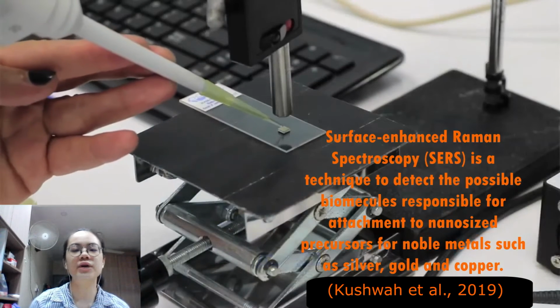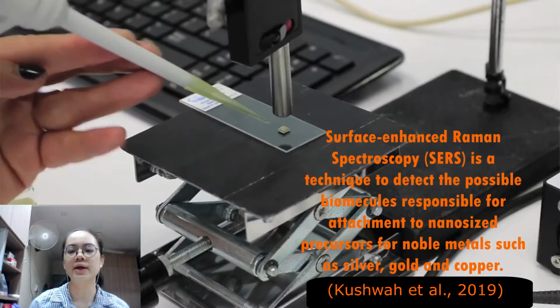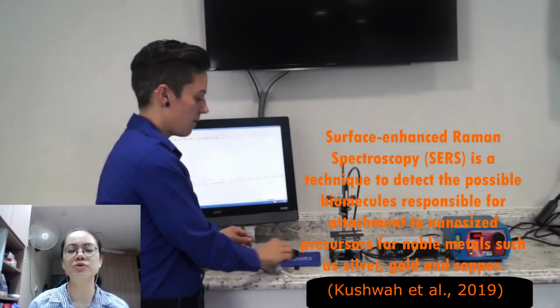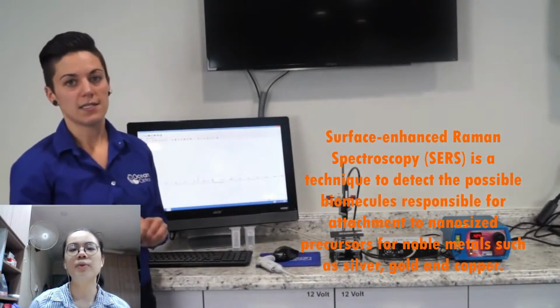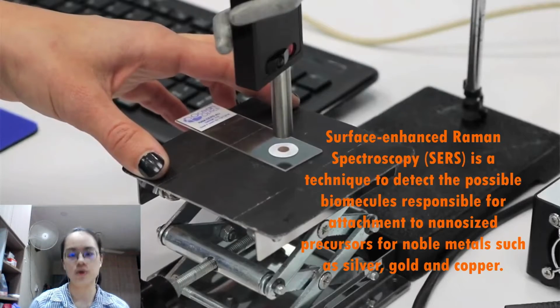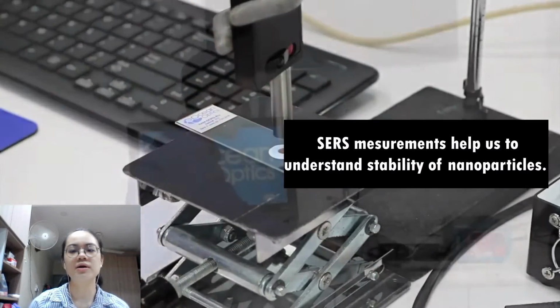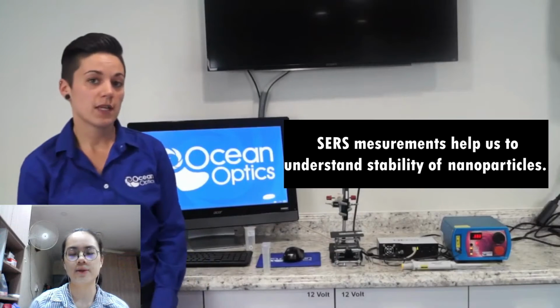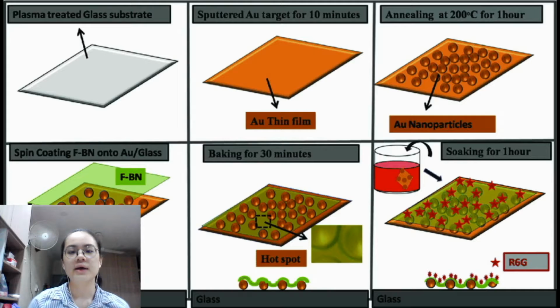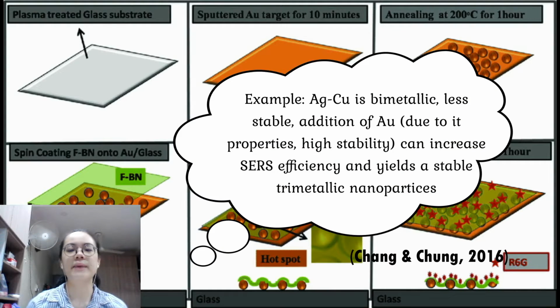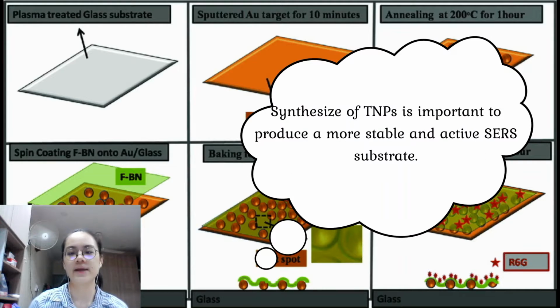SERS is a technique to detect the possible biomolecules responsible for attachment to nanosized precursors for noble metals such as silver, copper, and gold. SERS measurement helps us to understand the stability of nanoparticles. For example, silver-copper is a less stable bimetallic, and the addition of gold can increase the SERS efficiency and yield stable trimetallic nanoparticles. The synthesis of TNPs is important to produce a more stable and active SERS substrate.